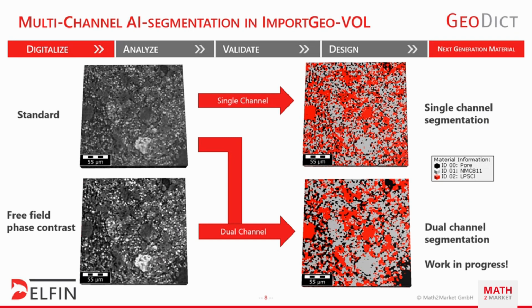It's basically the same approach that Roman showed before regarding the secondary electron images he used for the FIBSEM. Maybe I put your attention on this spot here. When you see it with your eye, you can pretty easily indicate that this is probably void space. Unfortunately, the single channel segmentation didn't agree with my eye test on this one, but if we use the dual channel segmentation, with the free field phase contrast image in the segmentation as well, we get a way better result. So in the end, we can take the relatively cheap and easy micro CT scan with 2 different reconstructions, and through the use of the dual channel approach, we are able to enhance our image quality significantly.